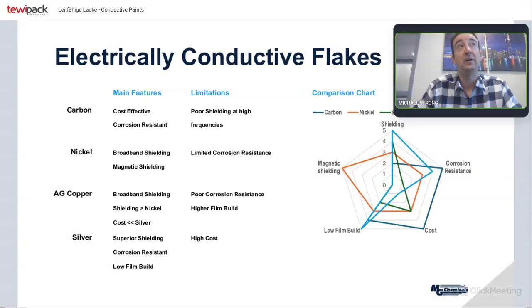And we actually did test that in our latest water-based nickel coating, and we presented the data in the technical data sheet. One of its limitations is limited corrosion resistance. This does not apply to every nickel product. The nickel acrylic coating actually did quite well when we subjected it to corrosion testing, but the epoxy and water-based did not. We're not exactly sure why, but we saw a significant drop-off in terms of its conductivity. And when you see that drop-off in conductivity, that is going to relate to its overall shielding effectiveness.